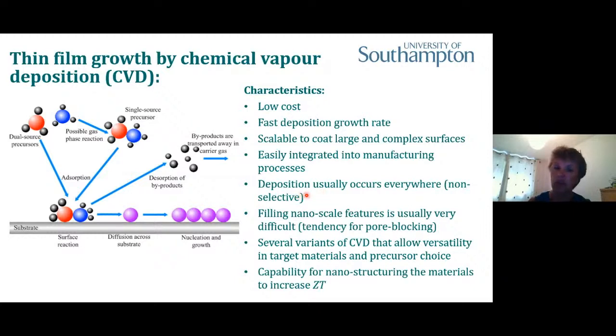One of the key things is that deposition tends to occur everywhere on the surface. So we would normally say CVD would be a non-selective deposition method. It's got some disadvantages. If you've got high aspect ratio pores, so deep pores in a structure, because the vapor is coming in from above the substrate and having to travel down the pore, what tends to happen is that the vapor contacts the top of the pore, and that initiates deposition and tends to block the pore. So that's often one of the disadvantages of CVD. There are also some variants that one can use, which means we can bring in different target materials and different precursors. And I'm going to be focusing on single source precursors for these sorts of materials.